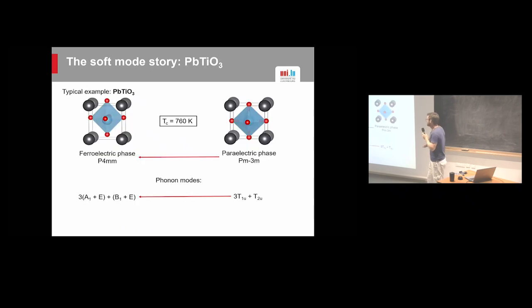So the first example that I have is lead titanate. That, to some extent, you have seen with Stanislav already. So I'll try to make it a bit shorter, just as a reminder. Lead titanate, a typical displacive ferroelectric, only one phase transition, super nice, cubic to tetragonal with a critical temperature at 760 K. In terms of phonon modes, we have this relation.